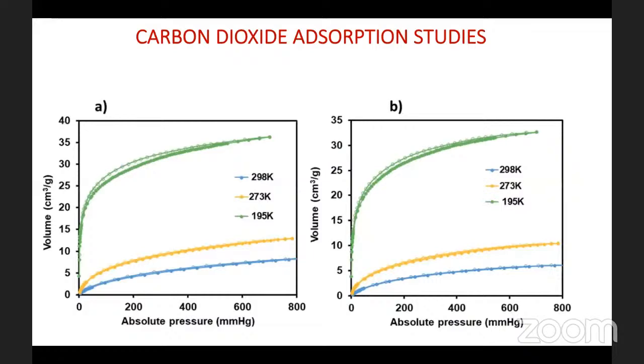We then did some carbon dioxide adsorption studies. A is the results for the as-made MOF before you insert your ruthenium complex, and B represents results for the ruthenium functionalized MOF, after inserting the ruthenium complex into the MOF. As you can see, at 298 kelvins, the amount of CO2 adsorbed by both the pristine MOF and the functionalized MOF is comparable. But the ruthenium functionalized MOF takes slightly less carbon dioxide when you compare it to your pristine MOF.